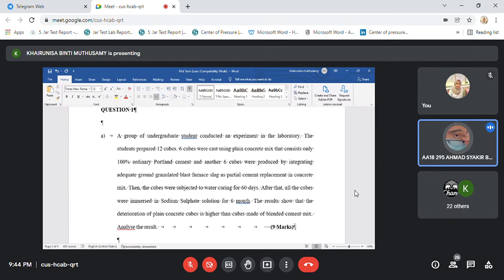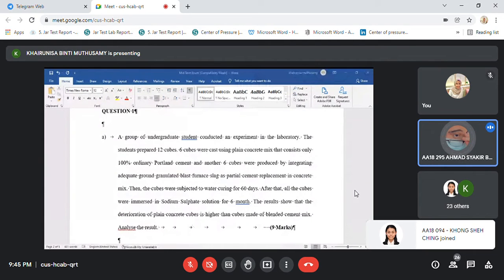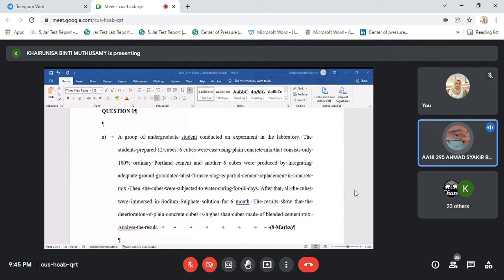Pozzolanic reaction will occur in the cube containing the ground-granulated GGBF slag, and as the cube is cured in water for 60 days, we know that pozzolanic reaction requires moisture, and then pozzolanic reaction can cause the addition of secondary CSH gel, which will fill in the voids in the concrete, in between the